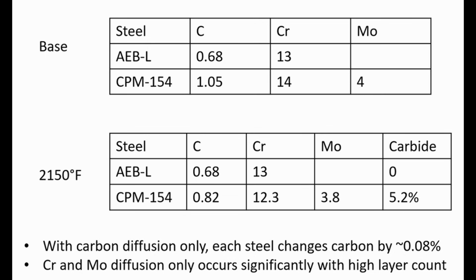Instead, it's the carbon that is still in solution that equalizes, and that would be about 82 points of carbon for 154CM. And so the 154CM is only going to lose about 8 points of carbon, and the AEB-L will gain about the same amount. So yeah, in that case, the carbon diffusion is quite small, even though there is a significant carbon difference between the two steels.